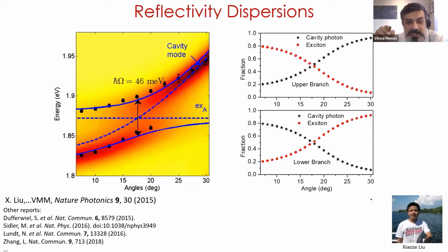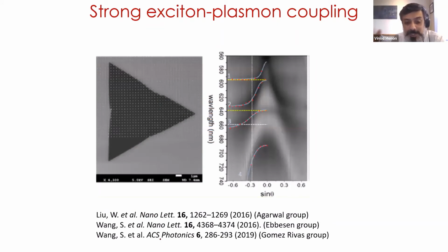This was work done by my then graduate student Xiaoze Liu, who is now a faculty in China. And there have been several other groups that have reported similar work soon after, and it's now become a field that a lot of people are exploring, even with plasmonic systems. So here is an example where people put plasmonic nanoparticles, and then they couple that to photons. The plasmons in the structure were coupled to the excitons, and they were able to show strong coupling in these systems. So the 2D materials present a nice platform to study strong coupling, simply because the oscillator strengths are large, binding energies are large, you can do it at room temperature. So even with losses in plasmonic systems, you can see these strong coupling effects in these systems.